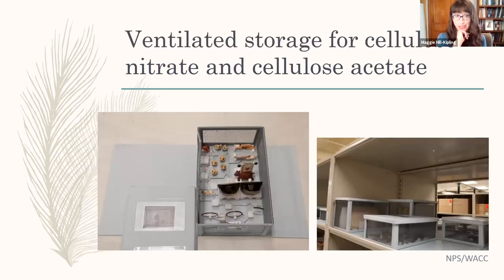But then there are other plastics like cellulose nitrate or cellulose acetate, which generate acidic vapors when they're in storage and when they begin to deteriorate. Those acidic vapors can be damaging, particularly to metals around them and to other materials, and they will continue to generate a cyclic degradation process if they're enclosed with acidic vapors. So one of the best ways to deal with that is to actually increase air circulation.